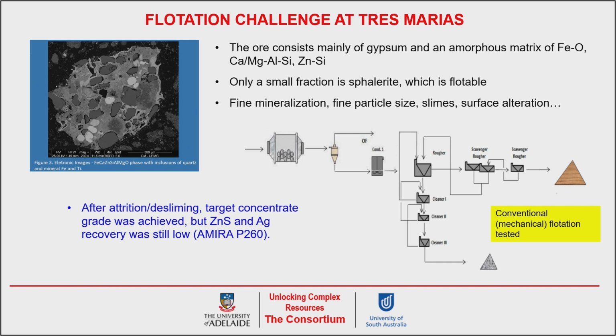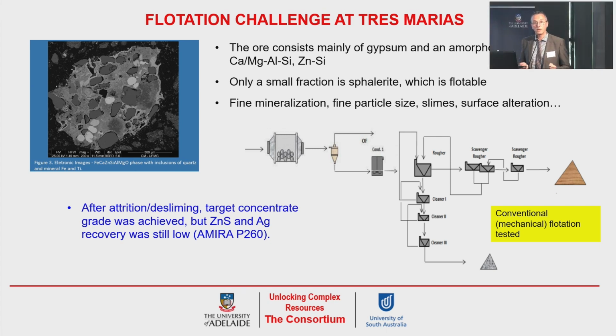So the strategy here was to start with attrition, to disperse the particles as much as possible, desliming to remove as much as possible of the fine gangue, and then flotation with a lot of optimization of the reagent scheme, because that material has been exposed to the environment for 40 to 50 years. So you can only imagine how the surfaces looked. We had to make them hydrophobic again.